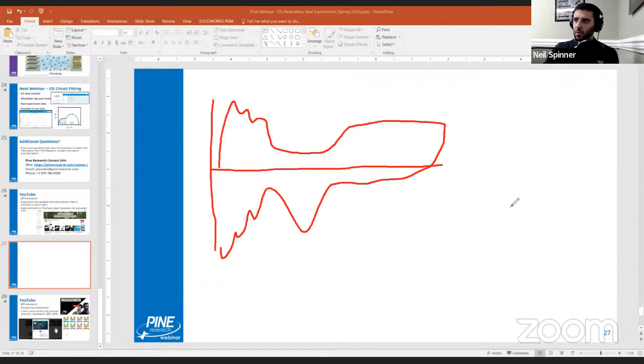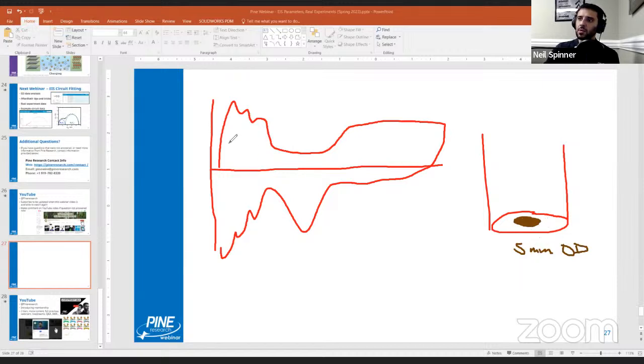Anyway, let's say you have a platinum electrode. So you have a disc and a shroud. I don't have silver, so all right, this is platinum. There you go, brown. Platinum's brown now. So here's my platinum disc. This is a 5 millimeter OD disc, or maybe you have a platinum on carbon film on your glassy carbon, whatever. So the point is you have some known geometric surface area. What people do to get the electrochemically active surface area is they do a simple CV in sulfuric acid.